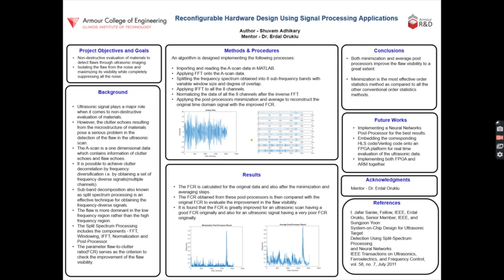The post-processor combines all the normalized signals coming from each channel to reconstruct the original time domain signal, but with an improved FCR. FCR, which is short for flaw to clutter ratio, serves as the criterion to check the improvement of the flaw visibility. The flaw is more dominant in the low frequency region rather than the high frequency region. Hence, the maximization of FCR highly depends on the number of channels, the size of the filters, and their degree of overlap. The FCR is calculated for the original data and also after the minimization and average post-processors.